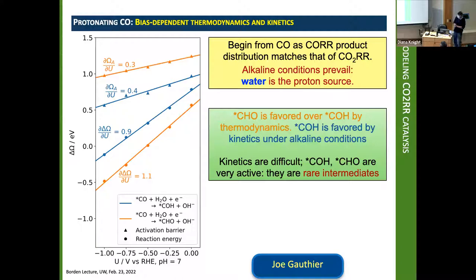On the x-axis is the applied bias, and on the y-axis is the free energy change, and the two lower curves correspond to the thermodynamics for making the first reduction to either the star COH intermediate, so protonate on the oxygen, or the star CHO intermediate, i.e. protonate on the carbon, and in either case produce hydroxide. And the two upper curves then show you the bias dependent barriers. So what you see is that as you charge the electrode negative, drive the voltage negative, the thermodynamics become favorable to produce these intermediates. Star CHO from CO becomes thermodynamically spontaneous. In other words, we're making that descending staircase for that first step.